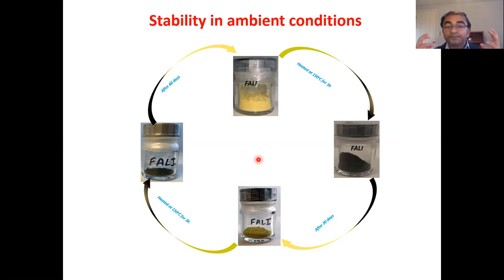Because in industry, you will need all these things. You will buy material from the industry and heat it. It is very simple heating, nothing required, only an oven. You heat the material for a particular time, you will get perovskite. You put the rest of the material in your oven or somewhere, and when you want to use it, you heat it for 1 hour, 2 hours, you will get perovskite, and you can use it. This is the stability in ambient conditions, and we are successful in that.